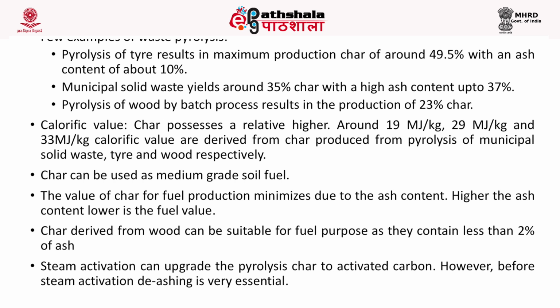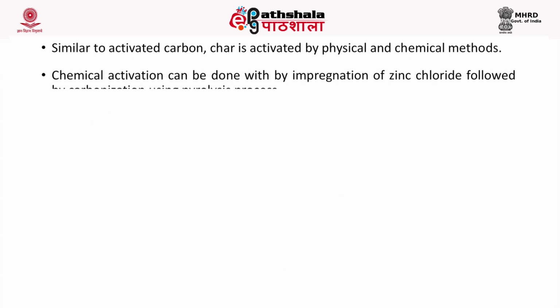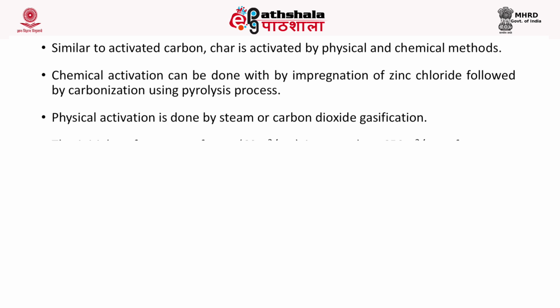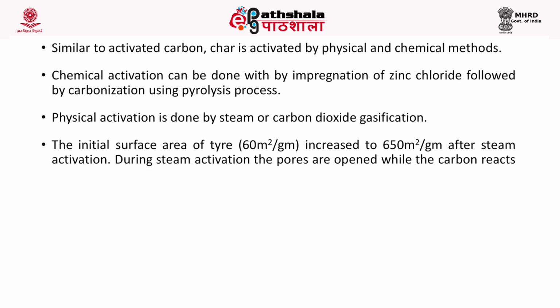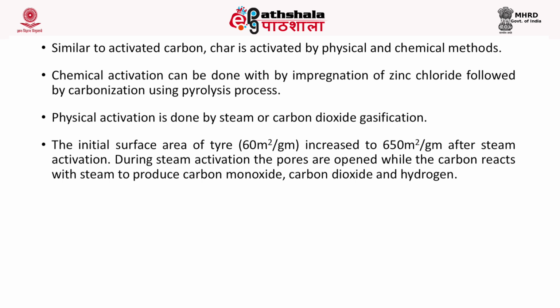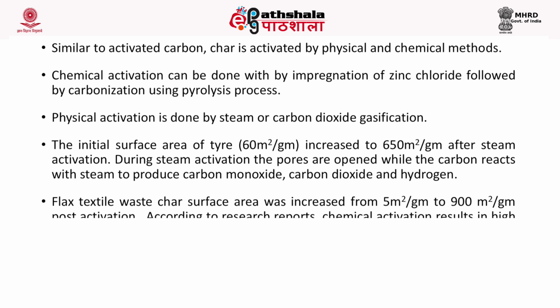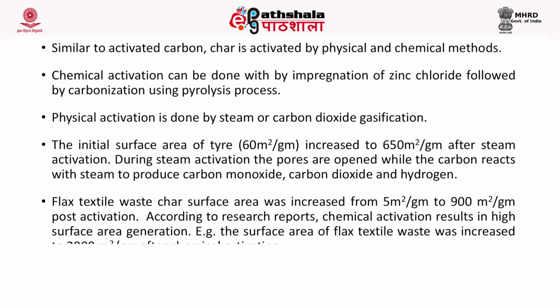Steam activation: now the char that is produced should be activated. The steam activation can upgrade the pyrolysis char to activated carbon. However, before you do the steam activation, de-ashing is very essential. Now, similar to activated carbon, char is activated also by physical and chemical methods. Chemical activation is done by impregnation of zinc chloride followed by carbonization, and physical activation is done by steam or carbon dioxide gasification. The surface area of tire char, which is around 60 meters square per gram, can be increased up to 650 meters square per gram after steam activation.